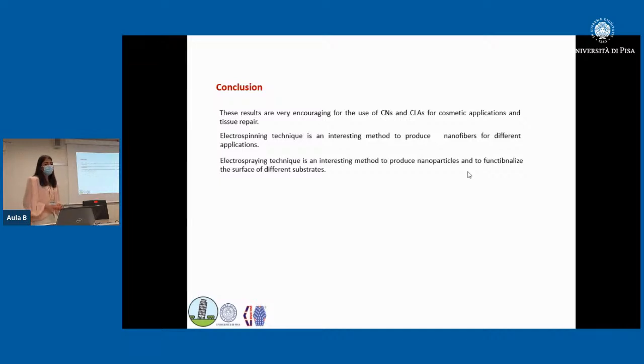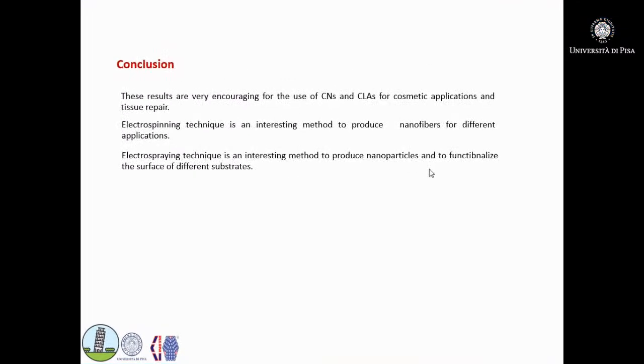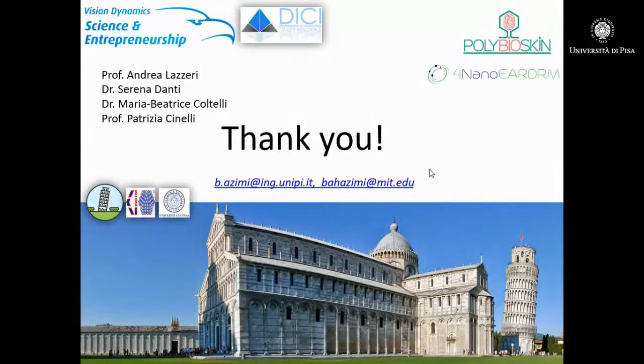So as a conclusion, I can say that these results are very encouraging for the use of this kind of natural, bio-based polymer, like chitin nanofibrils or chitin nanofibrils complex with nanolignin, especially for some skin contact applications like cosmetics or tissue repair. And electrospinning is a very interesting technique, because at the same time we are able to produce fibers and nanoparticles, and we can also use this technique to functionalize different surfaces, including nanofibrous mesh.